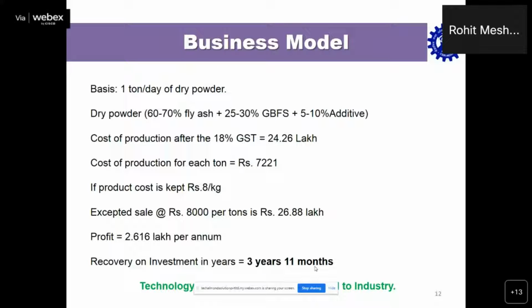So we have done the techno-economics for a 1 ton per day powder production. I'm not putting all the exact values, but the ranges are mentioned for the idea, and we have calculated the production cost after including the GST, and it is around 7,200 per ton. So based on this, the recovery on investment is only nearly 4 years, which is acceptable. Below 5 years is acceptable in the industry.